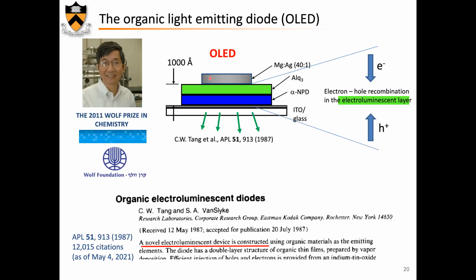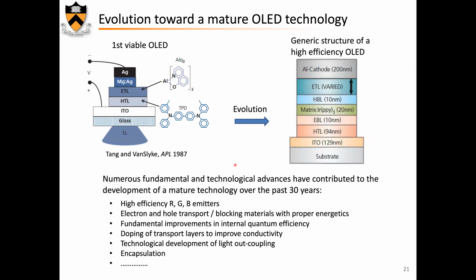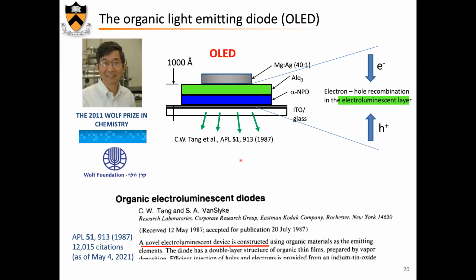But basically here, this magnesium silver contact injects electrons into this ALQ3, which is a green emissive layer, and holes are injected from indium tin oxide into this hole transport layer, alpha-NPD, and then recombination occurs in ALQ3, giving you this green light. Now, things, of course, have evolved considerably. The first device had rather low efficiency.